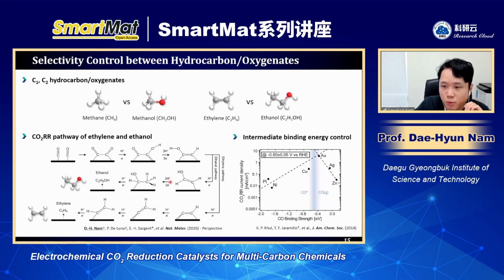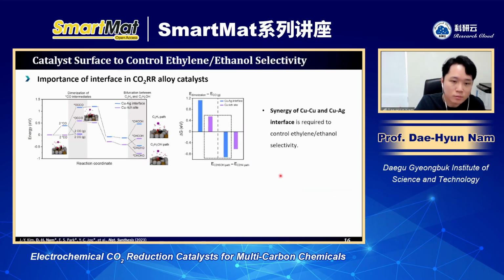So to control the pathway, we need to control the binding energy of the intermediates by applying some alloying. It means that we have copper as the major active site, and if we apply some other elements which can tune the binding energy of the intermediates, we can control the selectivity between ethylene and ethanol. And our research has started from this idea.